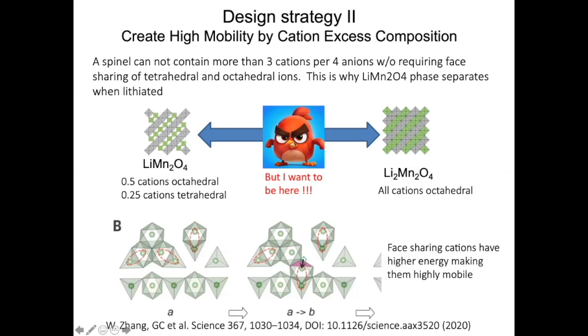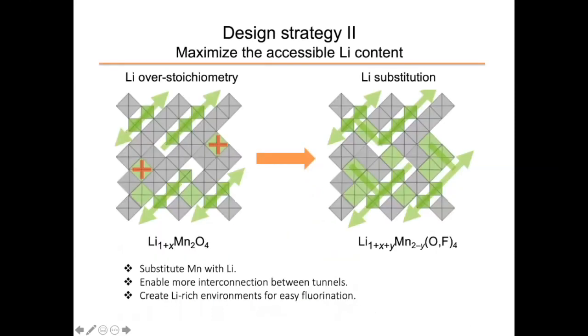The reason is that we now understand from work on anodes, cathodes, and conductors that if you have face sharing cations, you get high mobility. This was shown in a paper we did with Feng Wang, that this is the reason lithium titanate is a very high rate spinel: when you add a little bit of lithium, it creates these metastable face sharing contacts where a tetrahedral and an octahedral ion face share, and you could think of it as a high energy defect, and that high energy defect now moves very fast. So what we want to make is a spinel with these high energy defects so that we have high rate capability. We want to make the material cation excess, and we also want to make it lithium excess, because then we will have a lot of lithium to cycle back and forth, we will have lower cation repulsion, and we can fluorinate it if we have lithium excess.